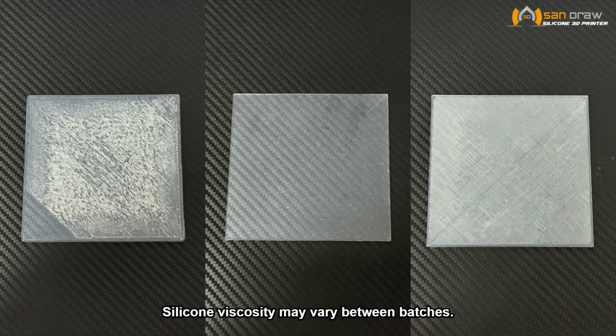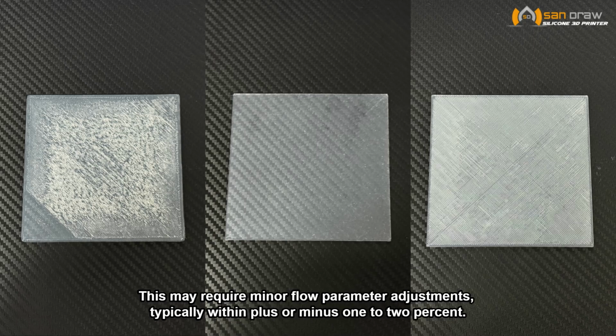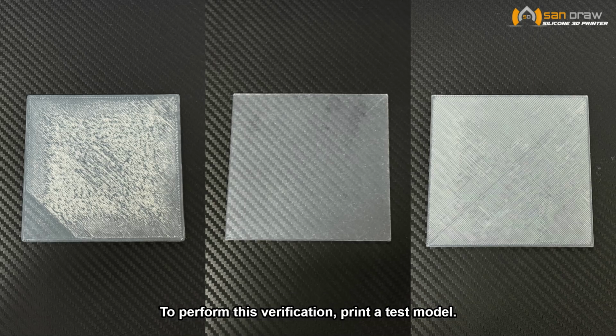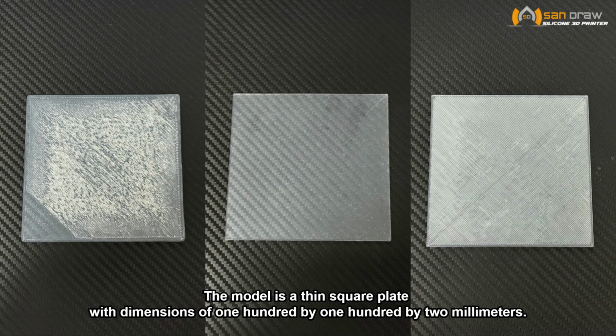Silicone viscosity may vary between batches. This may require minor flow parameter adjustments, typically within plus or minus 1 to 2%. To perform this verification, print a test model. The model is a thin square plate with dimensions of 100 by 100 by 2 millimeters.